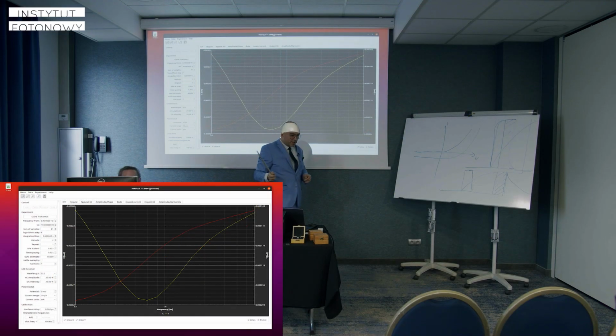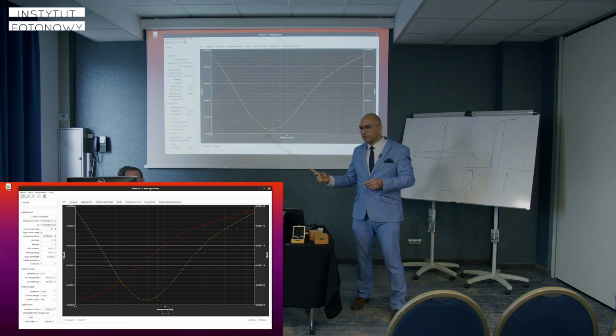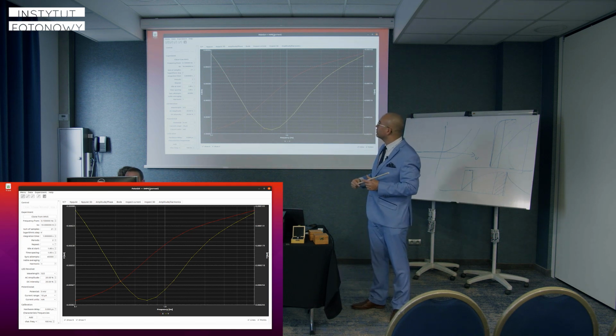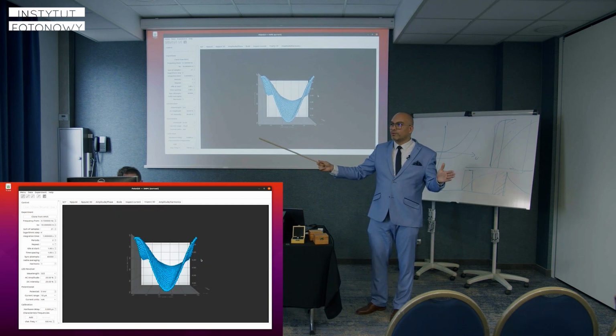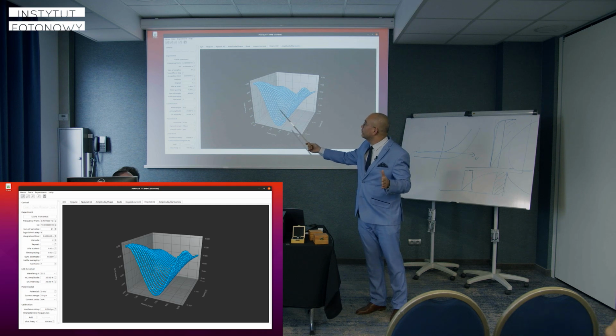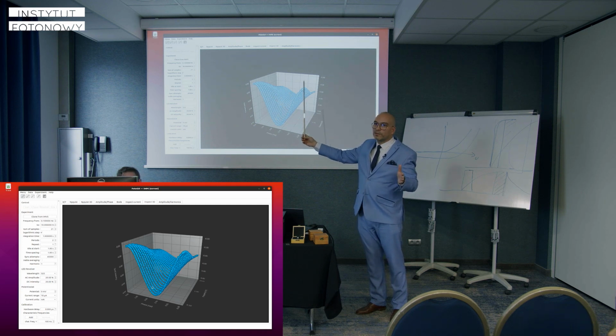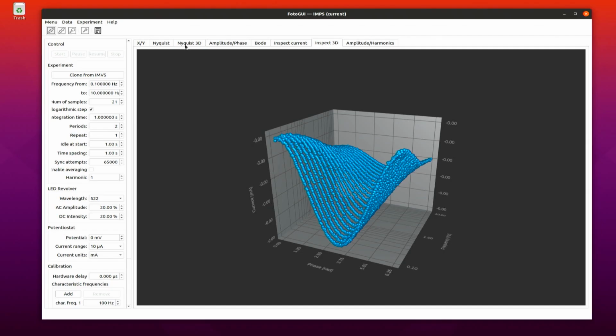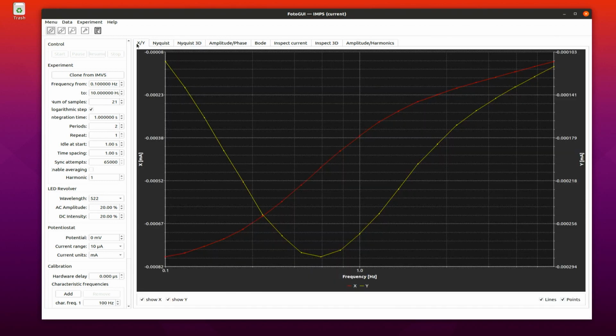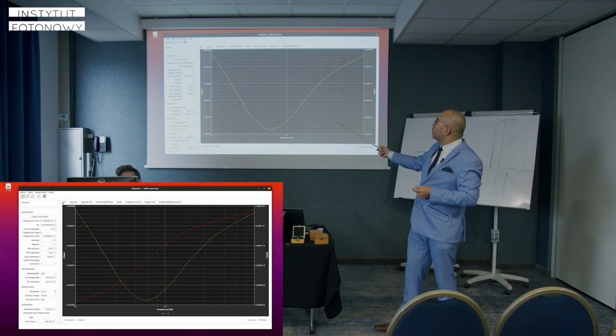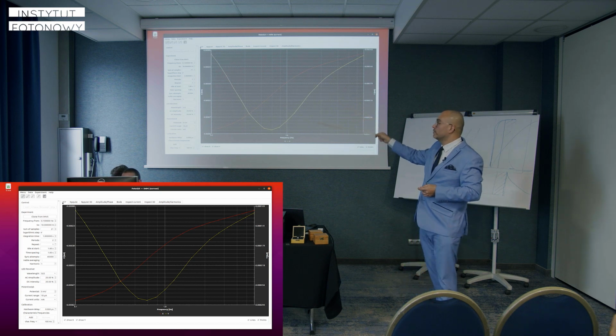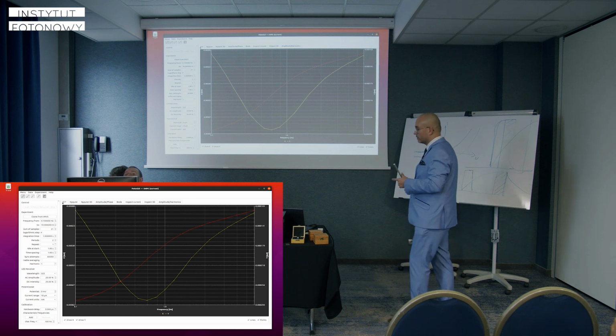we can handle very slow samples with frequencies down from some milli or microhertz. So to record one full period in case of 0.1 hertz, we need 10 seconds. If we start from 0.01, then for one full period we need 100 seconds, and to respect your time, we are not going to perform a whole experiment, so we just uploaded some previous results. All results that you are measuring, you can save to file and then upload again for study.